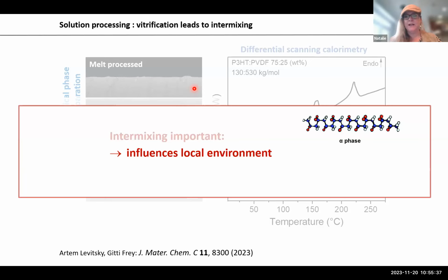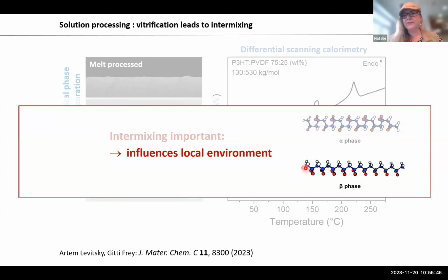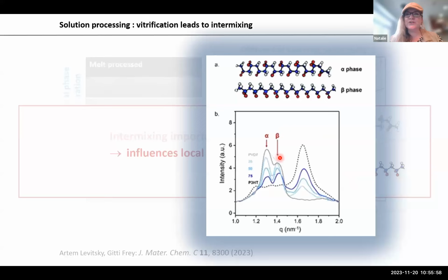Why is this important? Having this amorphous intermixed phase, we can really influence the local environment. As mentioned, PVDF can have either the fluorines up and down, so this one is an apolar phase, or you can have the beta phase, which is polar, where all the fluorines are on one side. So you actually have a dipole from plus to minus. And when we blend it, you see the PVDF characteristics in X-ray diffraction: the more P3HT we add, the more beta phase we have with respect to the alpha phase.